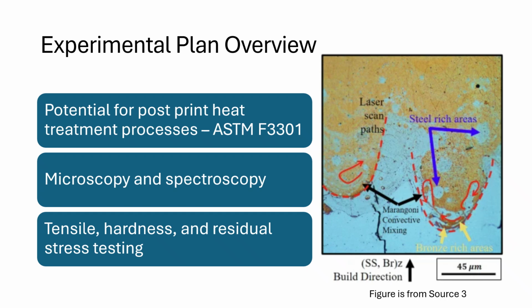After fabrication, parts will undergo hot isostatic pressing and heat treatment. Hot isostatic pressing is a post-processing method that uses high heat and pressure to densify 3D printed parts and close voids within them. I will use scanning electron microscopy and energy dispersive spectroscopy for coupon composition mapping. Electron backscatter diffraction and transmission electron microscopy will be used for analyzing the parts' microstructures. Tensile tests following ASTM E8 and E21 will be used for determining the mechanical strength of the different prints. These ASTM standards cover both tensile testing at room temperature and elevated temperature, which is where these materials are most likely to see their most severe use cases.